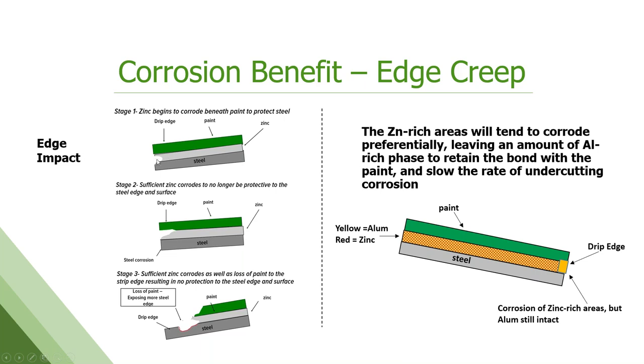So again, got a drip edge here. The zinc on galvanized starts to wear away, sacrificing itself. Now you have nothing holding the paint, so you've got this paint flapping out here in the breeze. It usually breaks off, peels off, which just accelerates the whole process because now more zinc is exposed. It corrodes. You're down to base steel and red rust. We call that edge creep, which is the progression of rust up from the edge of the panel.